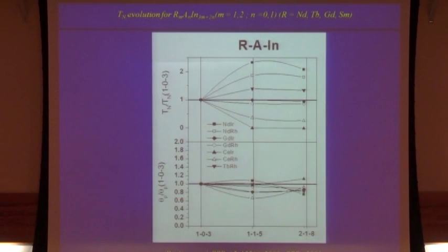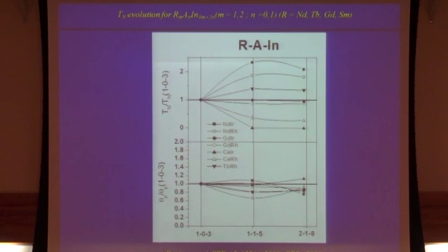Okay, so I can do something like that. For some of the compounds here, I can get cerium, I can get gadolinium, neodymium. I also deal with terbium, I deal with many. I'm just simplifying things here for you. And you can look at the magnetic order, you can look at theta, right? Which is associated with J in a molecular field approximation, which is associated with the mean field magnetic interaction, which is related to RKKY, in this case. But I can compare the evolution of theta with the evolution of T_N.